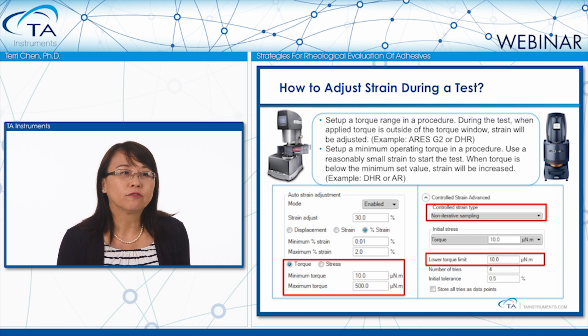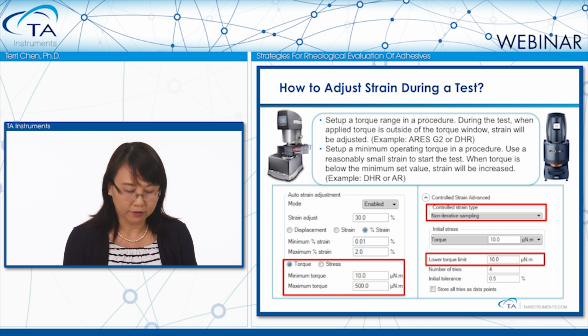The other method is for the DHR user. It is shown on the right side of the slide. In the main temperature ramp experimental procedure, the operator enters a small strain that is in the linear viscoelastic region for the entire test. Then, under the Control Strain Advanced tab, selecting non-iterative sampling, the software requires the operator to enter a lower torque limit. This lower torque limit is not the instrument low torque spec, but it is a smart way to help adjust the strain when the sample becomes really soft. Now let's take a look at an example in the next slides.